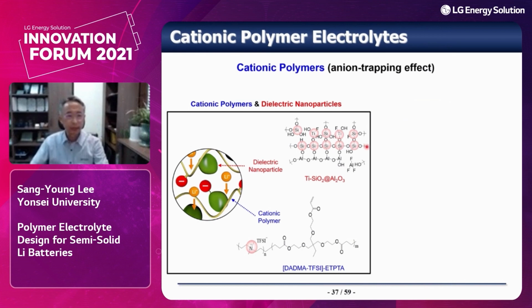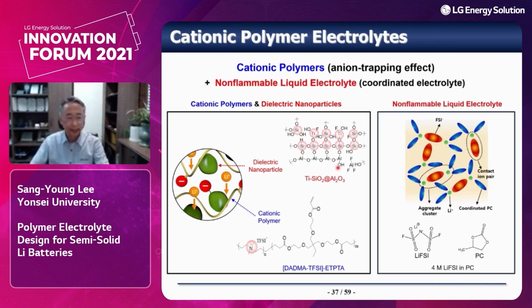Here are more details. We have designed cationic polymers enabling the anion trapping effect, and in addition, we have incorporated dielectric nanoparticles based on Lewis acid interaction. As the organic electrolyte, we have chosen a non-flammable electrolyte, which is different from the previous one. We designed LiFSI in propylene carbonate, which is also non-flammable, based on coordinated electrolyte chemistry.